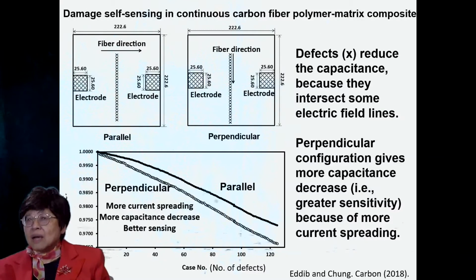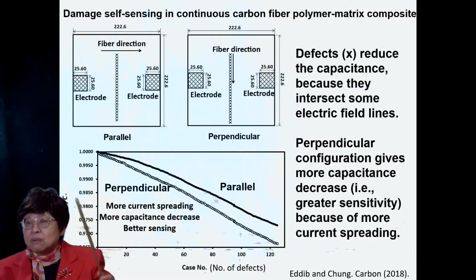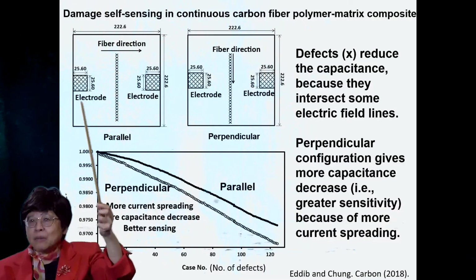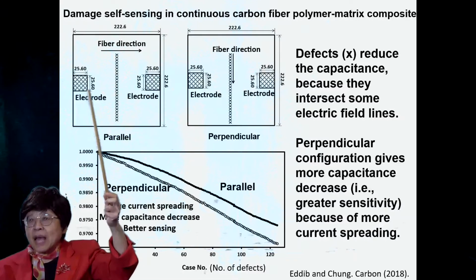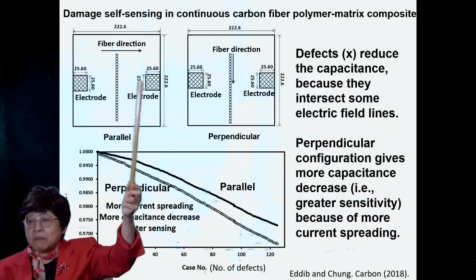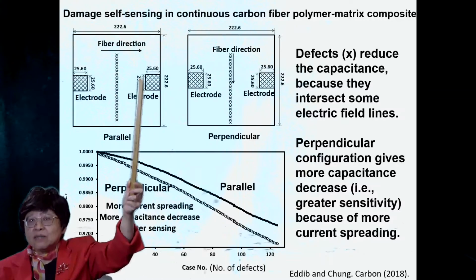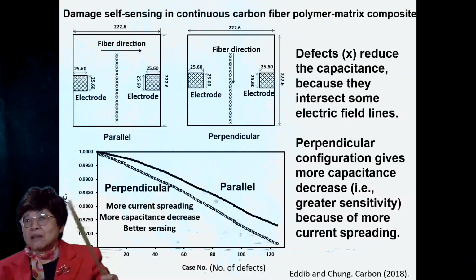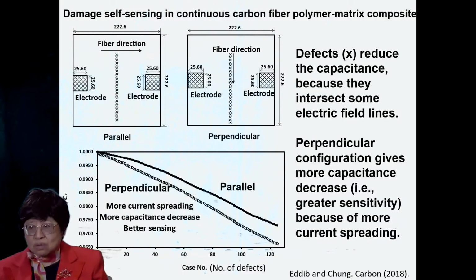One can also look at damage sensing, and this is the case of continuous carbon fiber polymer matrix composite with artificial damage in the form of tiny little holes making a row in the middle here. And we again use 2 coplanar electrodes on the surface. And so current bows out from the 2 electrodes, and the defects would intersect the electric field lines so that the electric field lines cannot spread so much, and as a result, the capacitance would go down. So the defects cause the capacitance to go down.